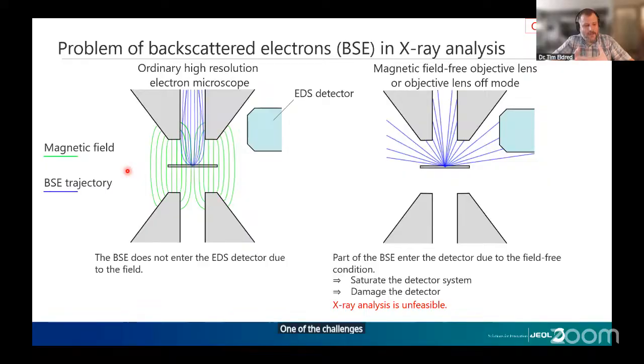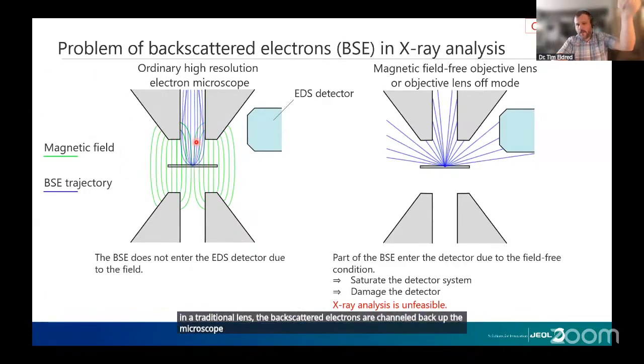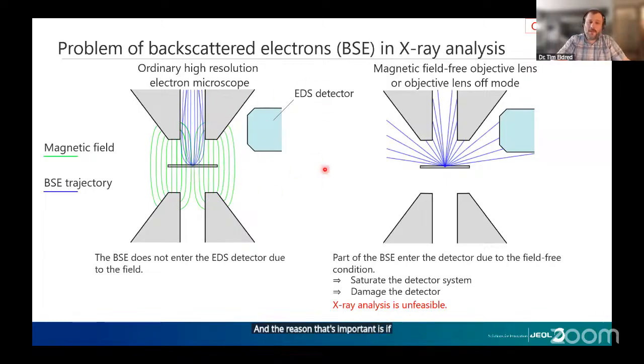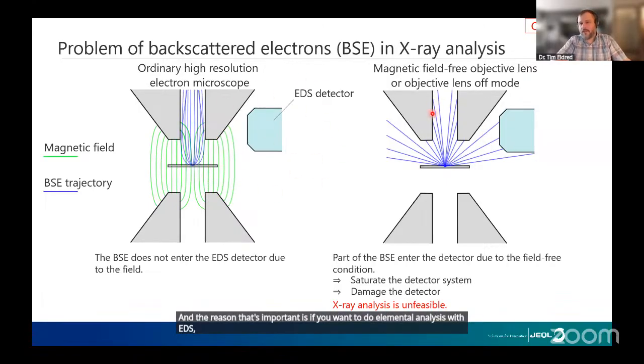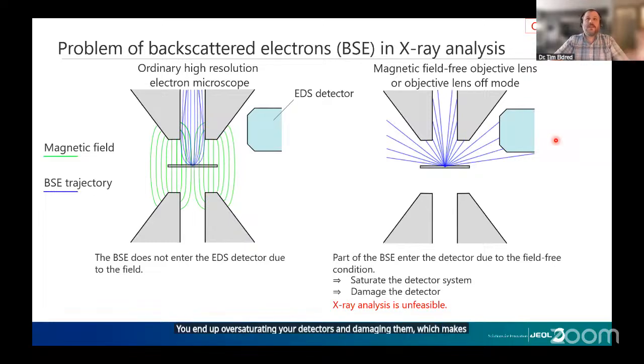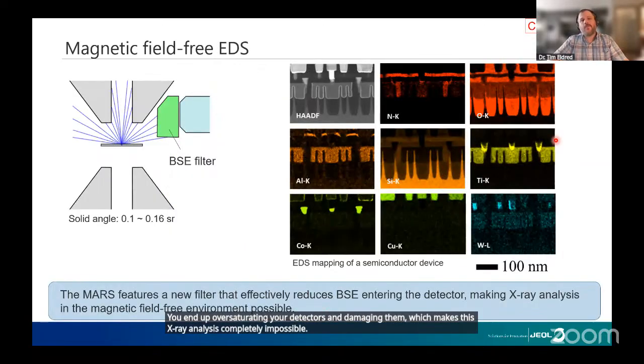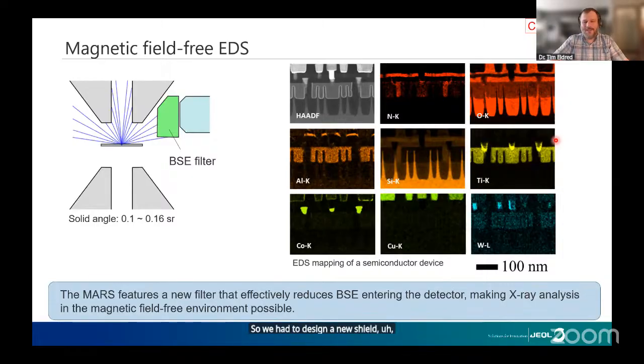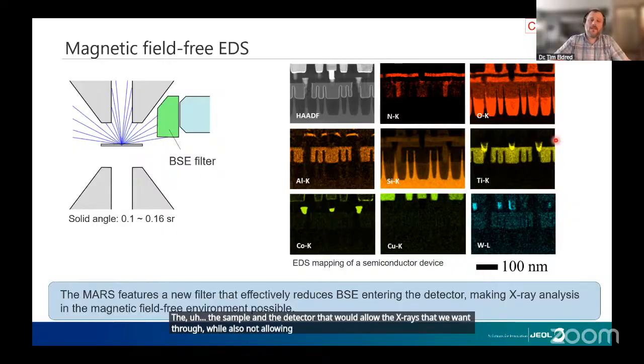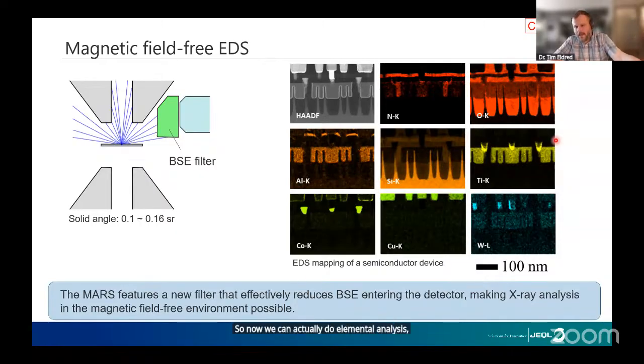One of the challenges of having a field-free sample area is backscattered electrons. In a traditional lens, the backscattered electrons are channeled back up the microscope. And the reason that's important is if you want to do elemental analysis with EDS, if those electrons are not channeled up, you end up oversaturating your detectors and damaging them, which makes this X-ray analysis completely impossible. So we had to design a new shield to go in between the sample and the detector that would allow the X-rays that we want through while also not allowing the unchecked backscattered electrons. So now we can actually do elemental analysis, unlocking another capability.